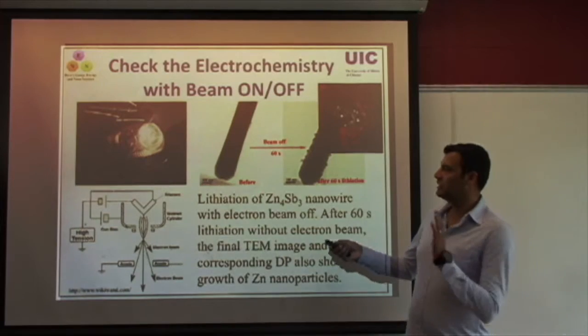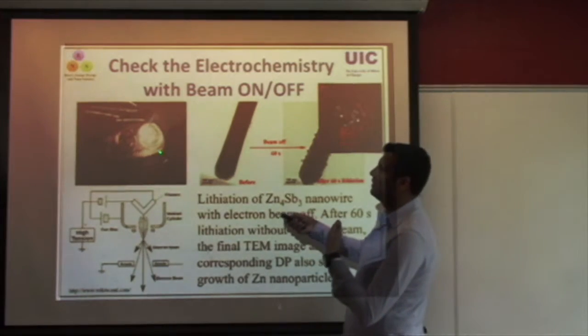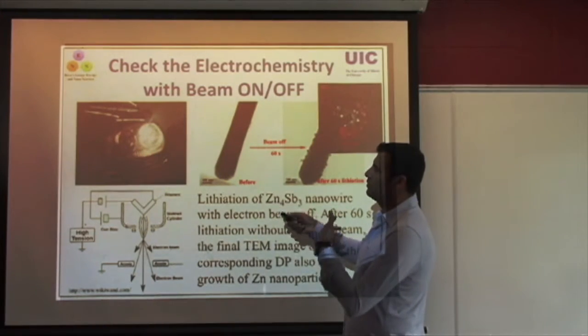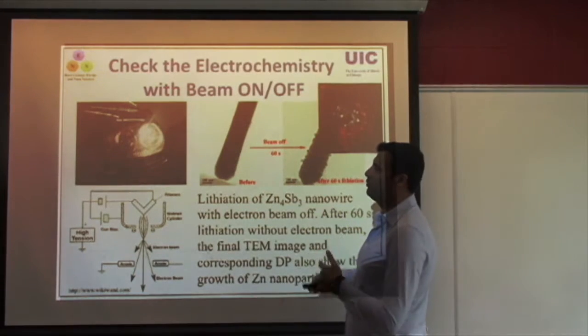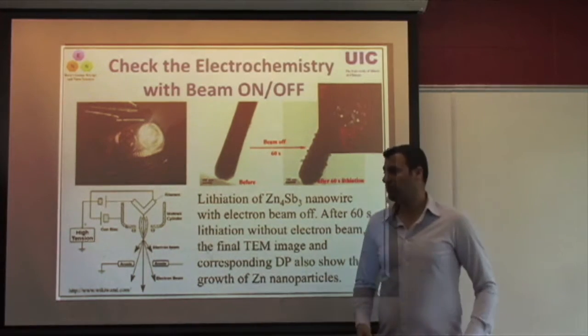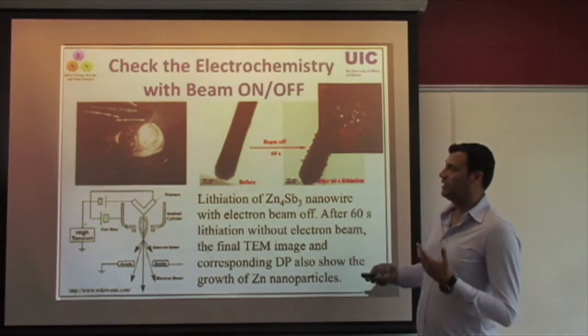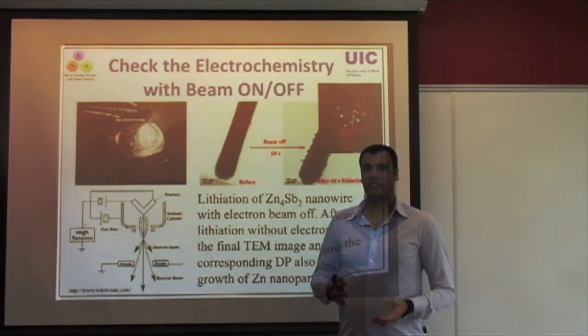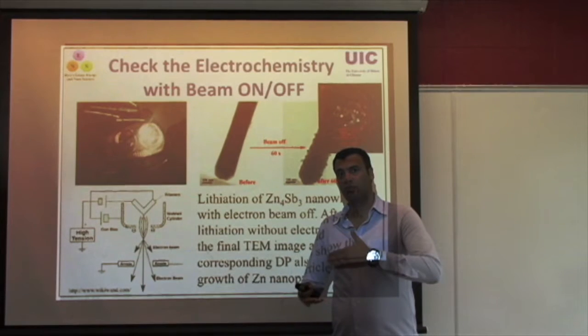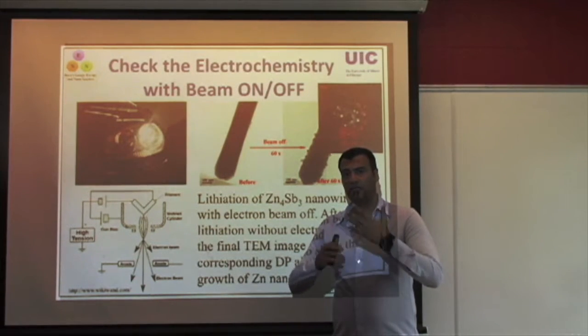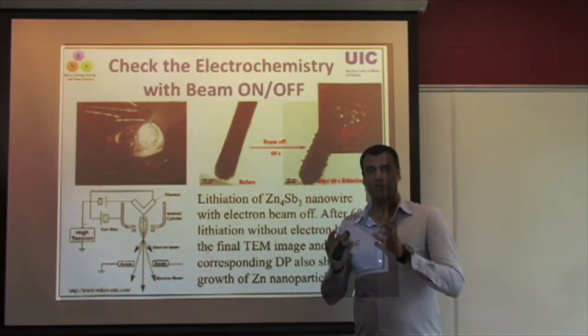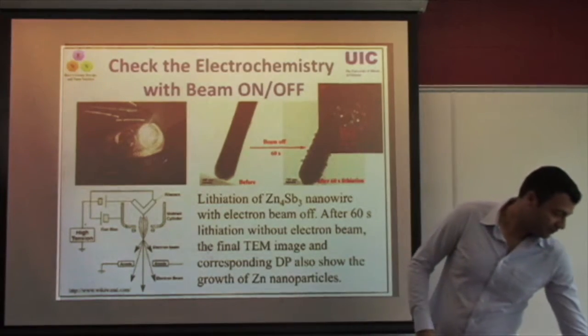I won't go too much into the details of this sort of thing, but we are able to control the beam, and there are several works we have already done and published in the literature by looking at the electron beam effect, basically blocking the electron beam, doing electrochemistry, and turning the beam on and off. So we can make a good correlation between these two cases.